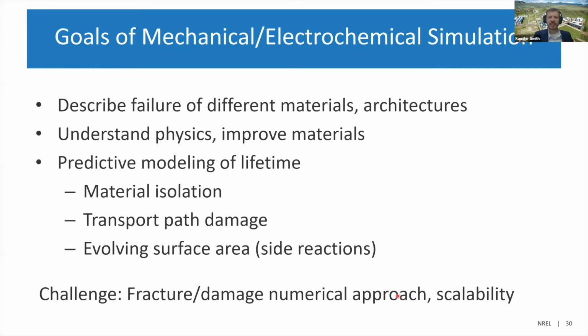Some of the challenges here are different descriptions of fracture and damage that exist in the literature, very different approaches that come about. And some of these we're not certain how high they'll scale in terms of the number of degrees of freedom. Our present microstructure model, when we solve that large volume of electrode that I mentioned, has about 25 million degrees of freedom.